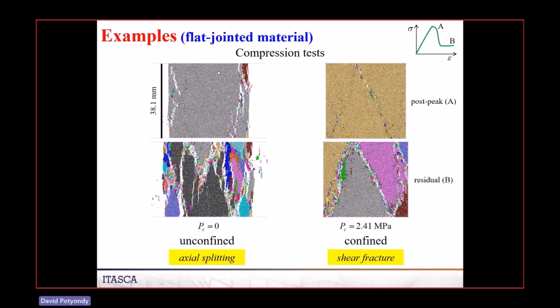All right. This is on the left, unconfined tests. This is in the post-peak region, and again, you can see this is right at the peak. And then if you continue to apply strain, so the stress has dropped almost to zero, you can see how it's breaking up into these axially aligned columns. And then if you do the same material, but you apply confinement, now you're getting this shear fracture.